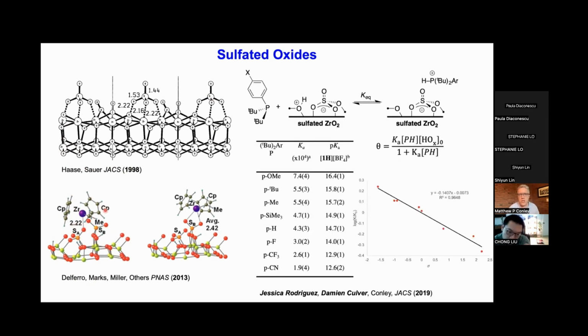So when we got into this area, we were interested in looking at this acidity problem, and we quickly confirmed many of the suspicions that the sulfated oxides are not superacidic in any way, shape, or form. What we did was look at phosphine binding to the sulfated zirconia surface to generate phosphonium ion pairs. This was a very well-behaved system that allowed us to experimentally deduce that these are not superacids at all, because we could actually measure the equilibrium adsorption constants using standard Langmuir-type isotherm fitting expressions. And what we can see is that as the X group on the phosphine becomes more electron donating, the pKa increases, which is exactly what you expect.